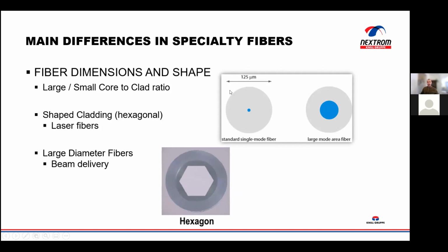Then the outer shape can be different. You can have different core to clad ratios, ranging from a very large ratio to a small ratio. Especially the larger core sizes are used in the fiber lasers. You can have shaped cladding. So this is a hexagonal cladding. And in this type of fiber, the pump light is put into the cladding, and with this non-circular shape, it will ensure that the pumped light will move into the core, where you have a doped core with the rare earth doped ions that I had mentioned earlier, and that's to create the lasing effect.